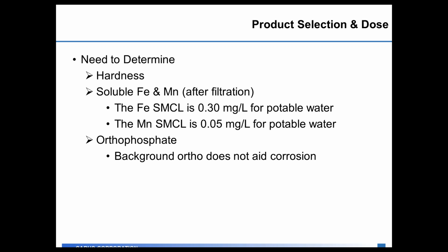We want to look at the orthophosphate if you're a groundwater plant, because you're going to have typically some background orthophosphate, and when we pick a product and a dose, you're going to take what your background orthophosphate is and add it to the selected dosage that's picked, and know that you need that combination. So if you had a background ortho of a half a part in some wells, and your target dosage is 1, you really need to see 1.5 in the distribution system to be at your target level of 1, because you have that half a part in the background.